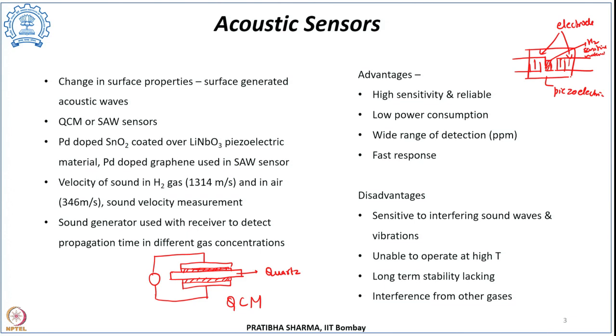Now, one of the electrodes converts the electrical signal into surface acoustic waves, and the other electrode converts that signal back into an electrical signal. Now, the difference between the input and the output gives a sort of signature of the hydrogen gas concentration, as there is an adsorption that takes place in the hydrogen sensitive film. Now, there could be different materials that can be used for the acoustic sensors, like the palladium doped SnO2, which could be coated over lithium niobate, LiNbO3, which is the piezoelectric material. Or it is possible that palladium doped graphene could be used in the SAW sensor, the surface acoustic wave sensors.